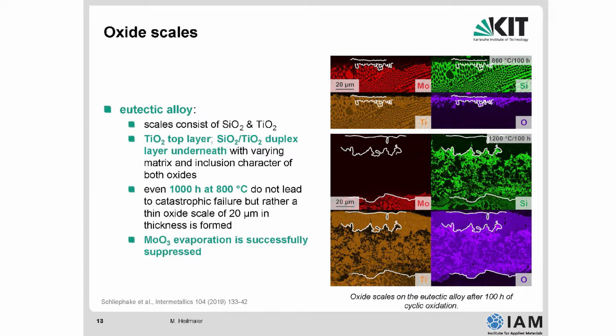And further to that, since the oxide scale is still very tiny, so this is 20 microns, so the oxide scale is about 5 micron thick, we can conclude that molybdenum oxide evaporation is suppressed successfully. And this is something special because those who may have worked with refractory metals know that all refractory metals, niobium, tantalum, molybdenum, tungsten, suffer from this effect. They form rapid oxides, and either they spall off the surface or they do sublimation and disappear. So this is not shown here, and this was found out for the first time for this particular alloy.